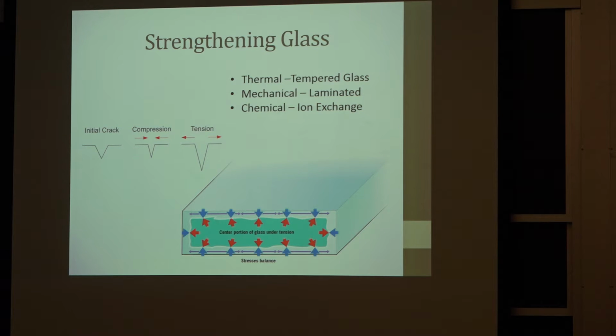The chemical process is an ion exchange, which exchanges the sodium ions. The raw material for the glass is basically sand, so sodium, and you have other materials. The ion exchange is used to strengthen the glass by exchanging the small sodium ions for larger ions. One of the ways they go about that is they can use a potassium chloride bath, so you would be exchanging the sodium ions for potassium ions. In that way, you can get residual stresses on the surface of the glass, and it's a strengthening process. We're going to be talking about tempered glass later. That's a thermal process. And there are some issues if you don't leave it in the tempering condition long enough. We'll talk about that when we get into glass fractures.